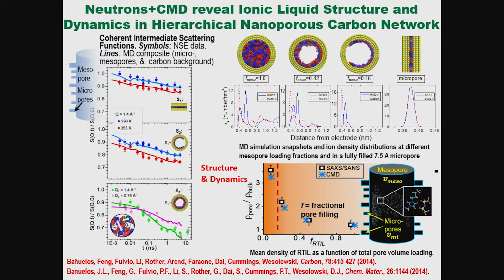We also did neutron spin echo experiments to probe the diffusional dynamics of those liquids in these various configurations. Again, we get a very good match between modeled and measured dynamics, and the bottom line is that we see slightly faster diffusive motion in this configuration than for the same ions decorating just the surface layer of the cylindrical pores. The origin of that is really disruption of the cation-anion correlation in these slit pore environments.